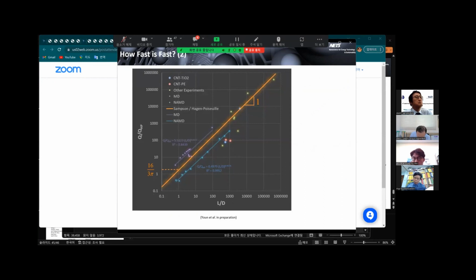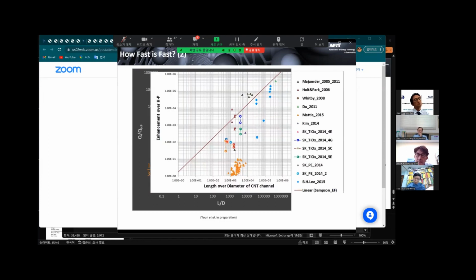The result is striking. Most of the simulation and experimental data are gathering around the maximum enhancement factor line. In this diagram, the orange maximum line divides the domain into an unattainable region, a maximum transport efficiency region, and a thermodynamically attainable region that the transport rate can sit in if the nanotube quality is imperfect and the flow resistance from the nanotubes takes part in the overall dynamics. Our experimental data lies in the region right below the maximum enhancement factor line, and the later published data supports our understanding too.